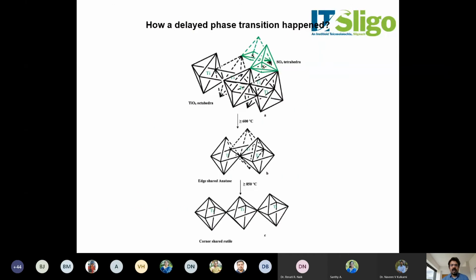So this is a scheme showing how the phase transition is delayed. TiO2 is made up of a number of TiO6 octahedra, and when the sulfuric acid was used, the precursor contains SO4 tetrahedra, and these octahedra were stabilized by SO4 tetrahedra, and then the anatase to rutile formation was delayed, and eventually there was no rutile formed up to a temperature of 850 degrees Celsius.